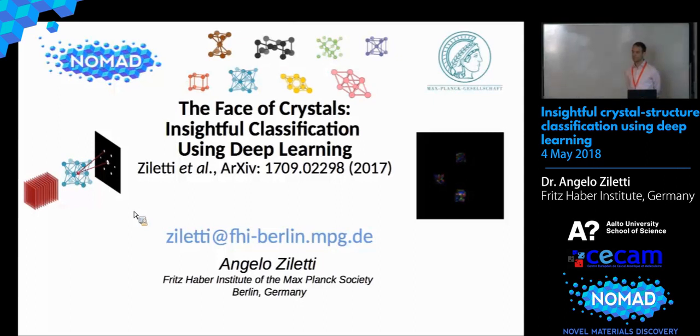Yes. I mean, we displace up to 0.08 angstrom, and we arrive at an accuracy of 99.91%. Around 1 angstrom displacement, it depends, of course, on your lattice. We show that up to 10% of the lattice displacement, so you get a lattice vector, it's still stable, and then you get a real drop in the accuracy, because in the diffraction pattern you really don't have a crystal anymore.